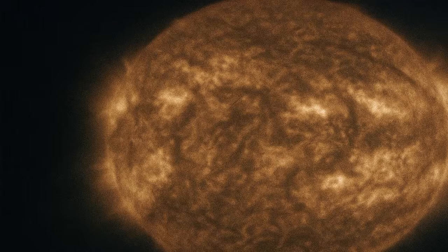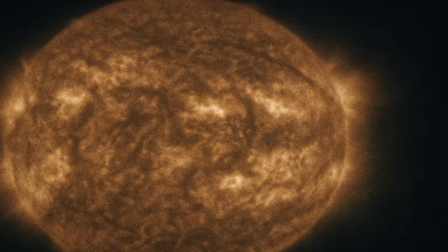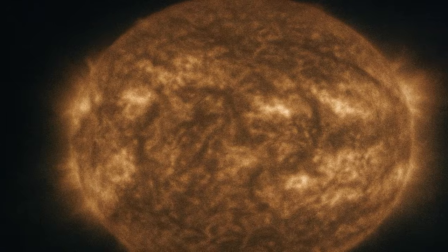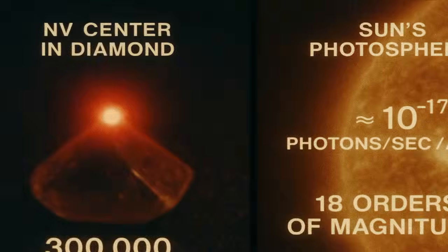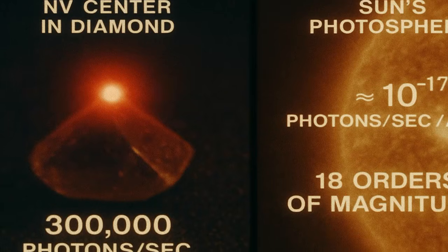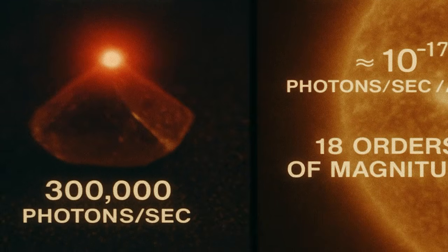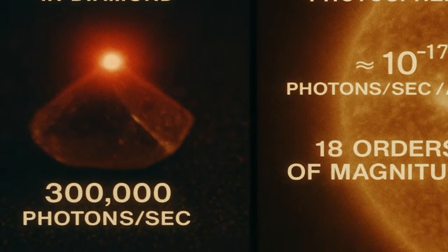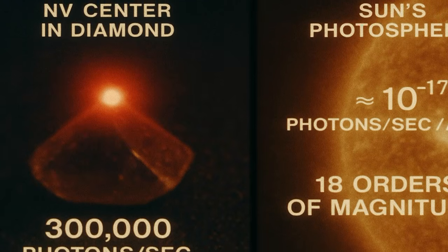The brightness comes from photon flux. One NV center excited at saturation emits about 300,000 photons per second. That's the count rate you get with a good confocal microscope and avalanche photodiodes. 3 times 10 to the 5 per second from a single quantum emitter. The quantum yield of 70 to 80% means most absorbed photons convert to emitted photons. Very little energy gets lost to heat.